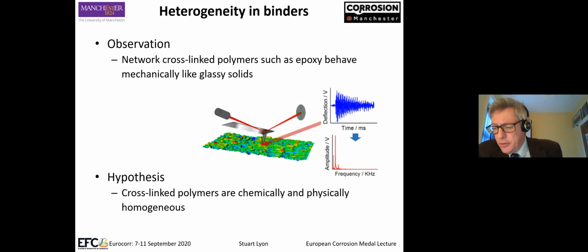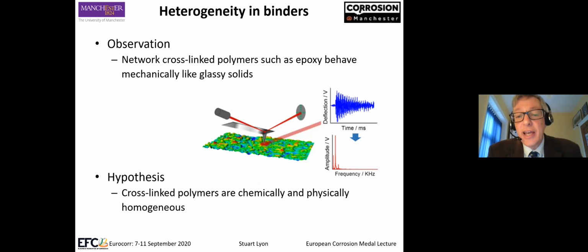So going from looking at how water and other species migrate, it's always been assumed, from the corrosion protection perspective, that there is some degree of heterogeneity in epoxy and network cross-linked polymers. But if you go to the perspective of the polymer scientists, they have always assumed that cross-linked polymers such as epoxy behave mechanically like glassy solids, and therefore they are almost certainly physically homogeneous and probably chemically homogeneous as well.